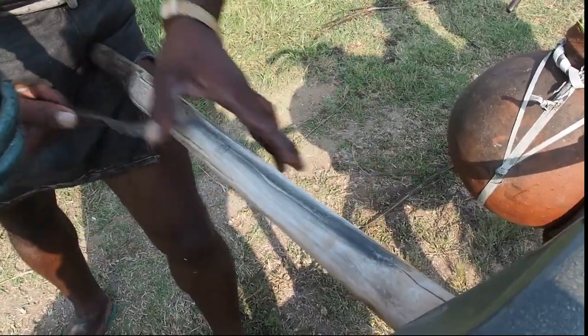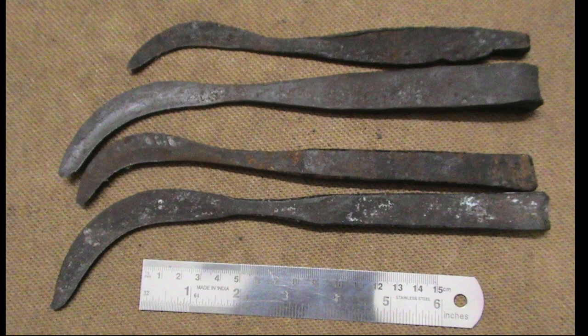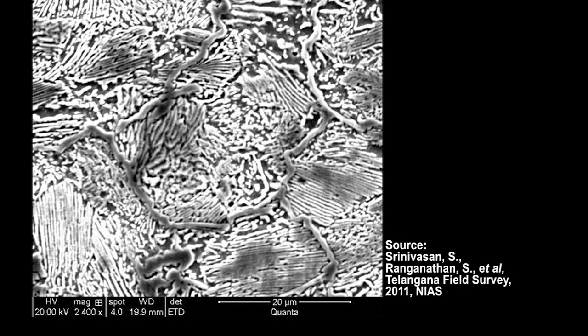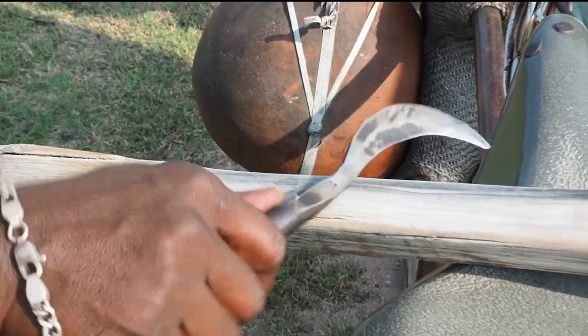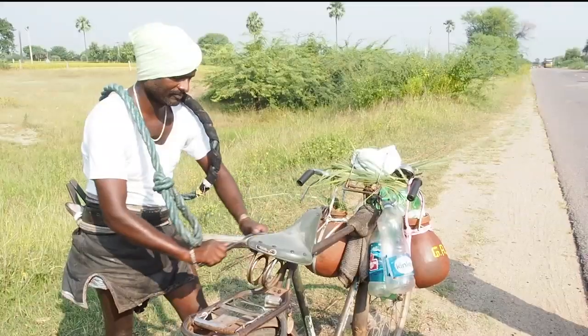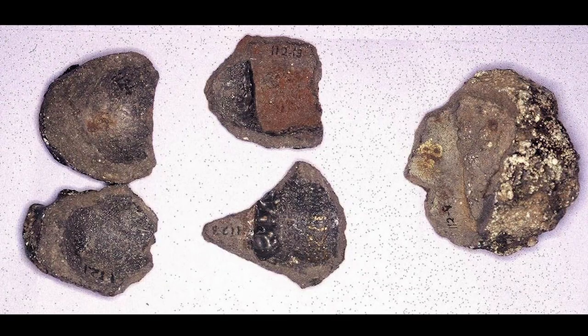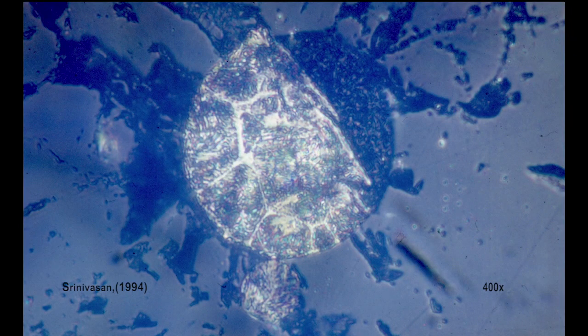It is interesting that a toddy tapper's knife was found to be of wootz steel, clearly showing a microstructure of hyper-eutectoid high-carbon steel of 1.5% carbon with dark perlite alternating with cementite. The production of hyper-eutectoid steel by the crucible steel process was indicated by microstructural studies on crucible fragments from antiquity from a production site at Melsirvalur in Tamil Nadu.